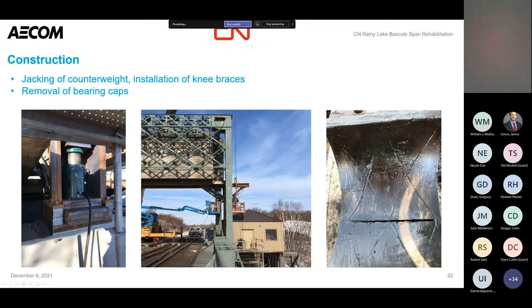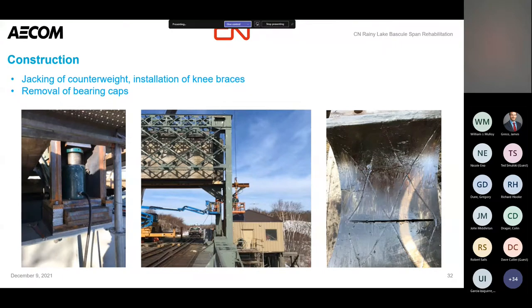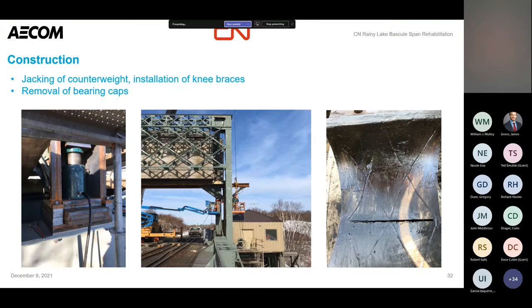On the left is a photo of their jacking box going ahead and lifting the counterweight, and the middle photo shows getting the knee braces tightened once lifted. Before jacking, they had to remove the cap — we wanted to just jack to displacement until we had zero force in the trunnion itself. The photo on the right shows one of the caps they pulled off so they could check displacement and know when they had lift-off. You can see the condition: this was a bronze bushing with X-pattern grooves showing no significant wear. The cap is really just there to cover the bearing sleeve, keep it out of the weather, and keep it well lubricated — it actually sees no force between the cap and the bushing itself.